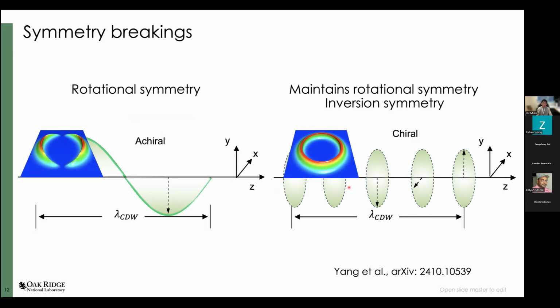Of course, we can talk about why the C2 versus the chiral density wave is more energetically favorable. The lattice energy is always dominant, but we can also think about the condensation energy of the Fermi surface. Here you can imagine for a C2 charge density wave, your CDW gap would be highly anisotropic versus an isotropic CDW gap for this chiral CDW.